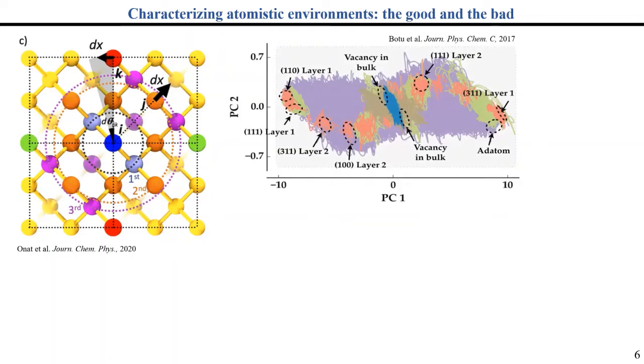One of the drawbacks is interpretability. If I pick a random point in this PCA space, where each point represents an atomic environment, I can't say for certain which area in the phase space that point belongs in. If I pick a point somewhere in the middle of those brown and red regimes, I can't confidently tell you if I have a surface, a grain boundary, some sort of bulk-like vacancy area, right? There's no way to say for absolute certain that, yes, this is my environment.